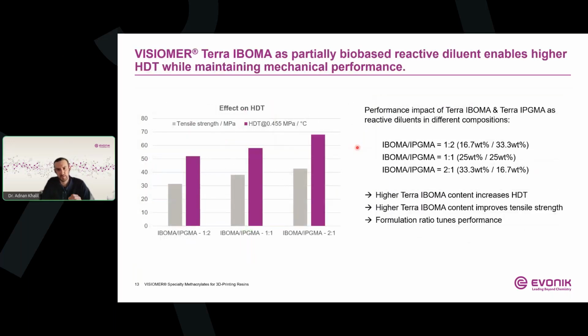To demonstrate this effect of the Terra Iboma in a photopolymer formulation, we compared different ratios of the Terra IBOMA and Terra IPGMA as a reactive diluent, while keeping the remaining resin composition in the photopolymer formulation constant. So what can be observed here on the left is very clearly that increasing the Terra IBOMA content leads to an improvement in the thermal performance, in this case indicated by the heat deflection temperature. So as the proportion of the IBOMA increases from a 1 to 2 ratio to a 2 to 1 ratio, the heat deflection temperature increases significantly.